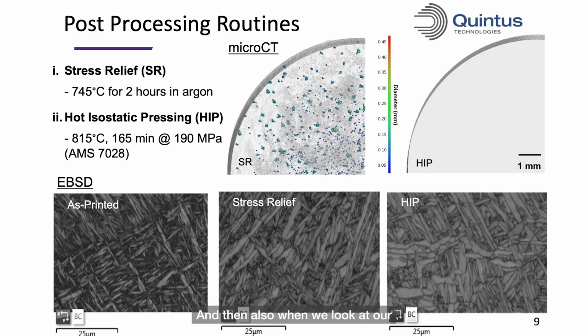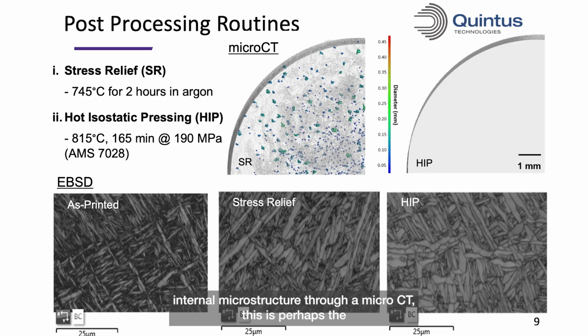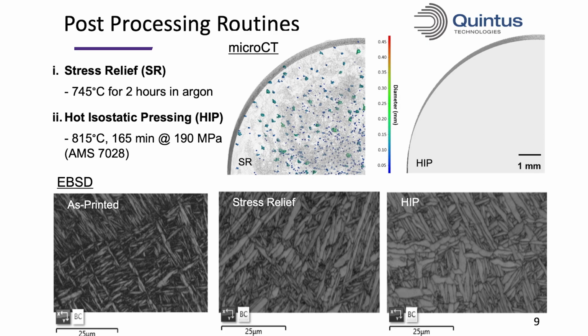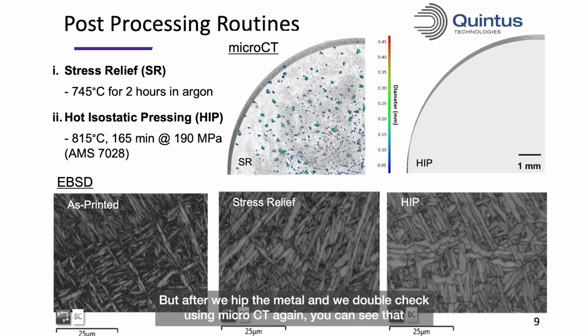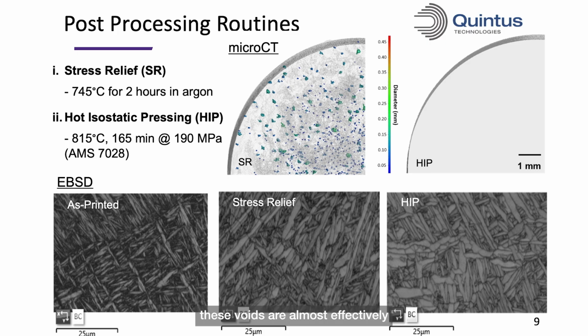And then also when we look at our internal microstructure through micro CT, this is perhaps the most beneficial factor for the HIP process in laser powder bed fusion. You notice that in the stress relief state, there are numerous voids and internal anomalies present. But after we HIP the metal and double check using micro CT again, you can see that these voids are almost effectively eliminated entirely due to the heat treatment. This is very beneficial, especially in fatigue applications.